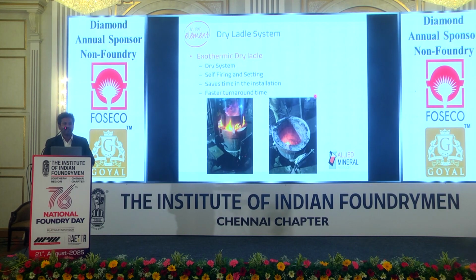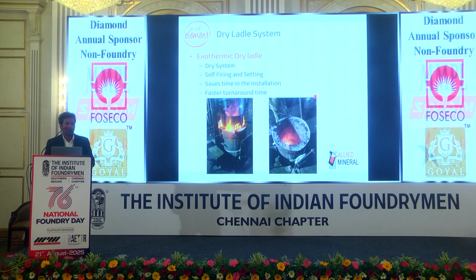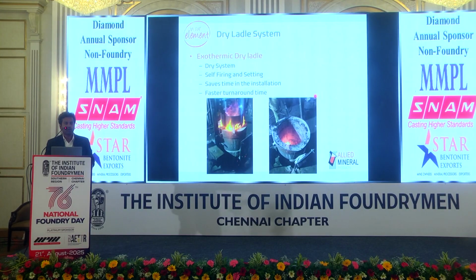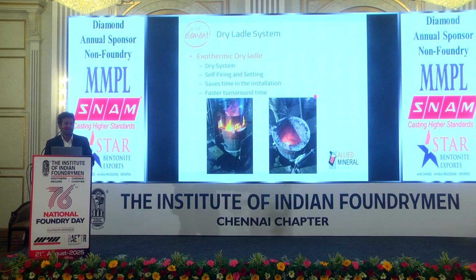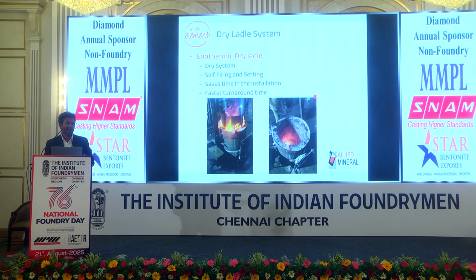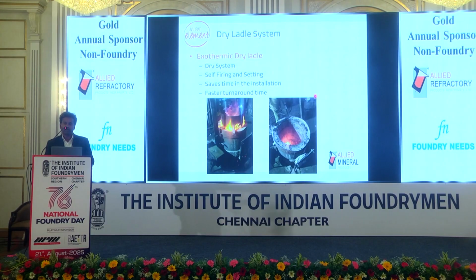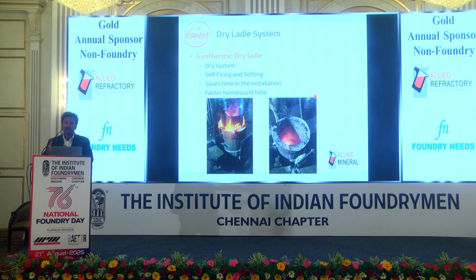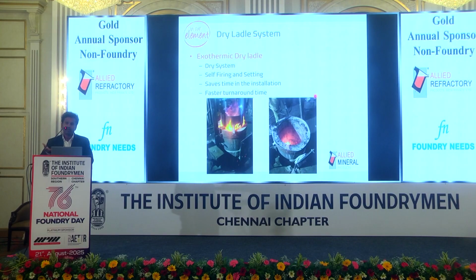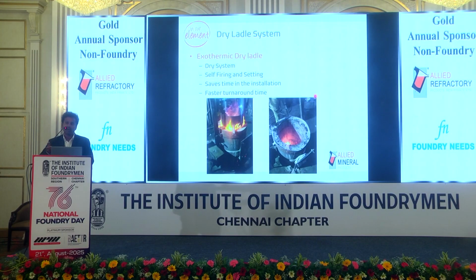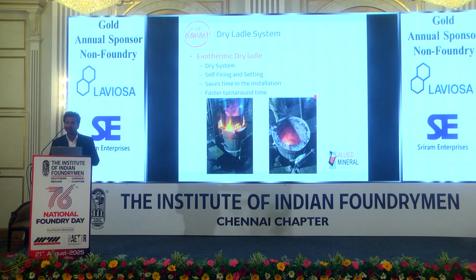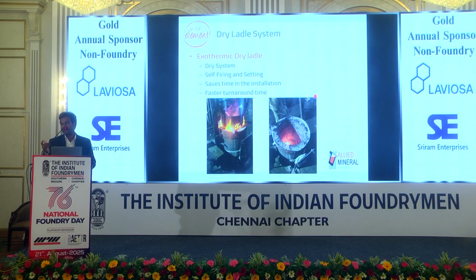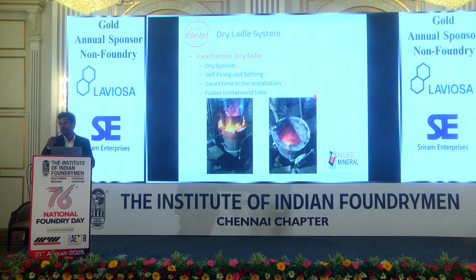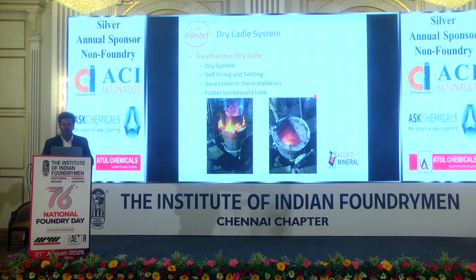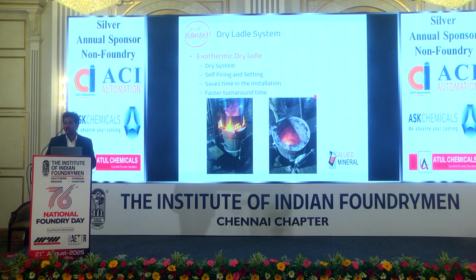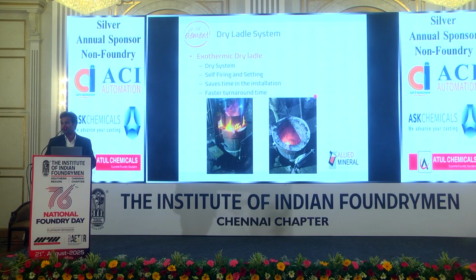Next comes a completely dry system. Depending upon the requirement, we can select the refractory accordingly. This system contains special additives which can be self-firing. You have to line your ladle the same way as your induction furnace. You have to ram, compact, and build up in layers. After you finish, you have to ignite the former either by torch or wood firing. The self-firing additives will activate, fire and harden the material, and it gets sintered. Within 3 to 4 hours, your ladle is ready to go. You can preheat the ladle and pour the metal in it.